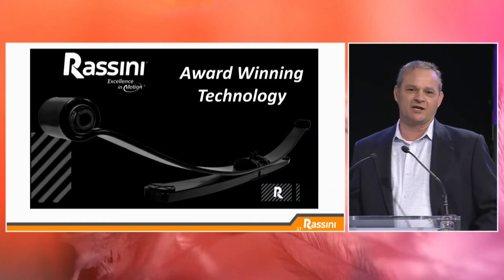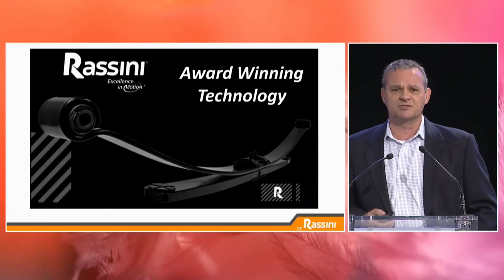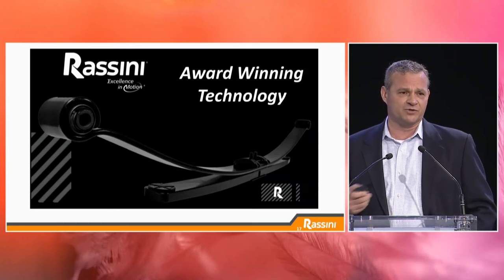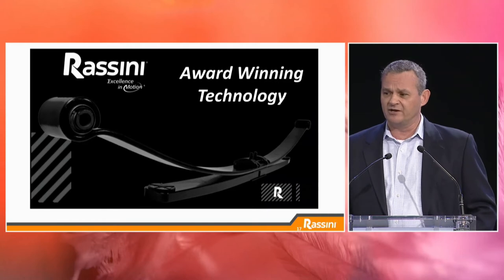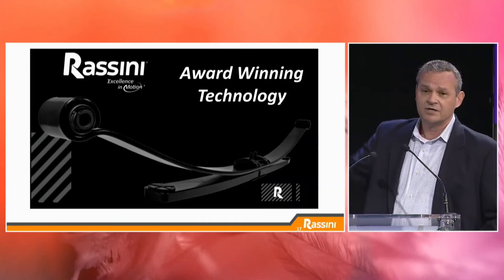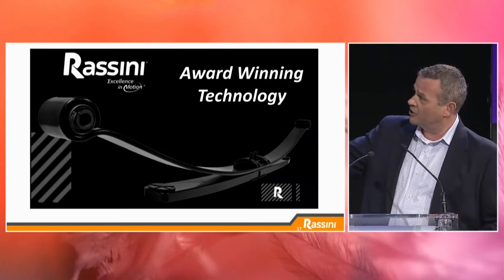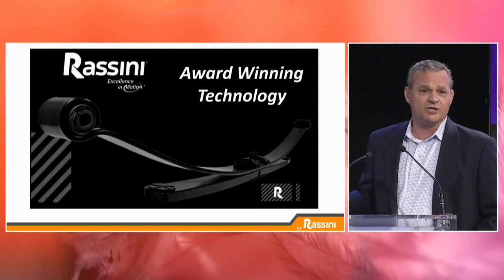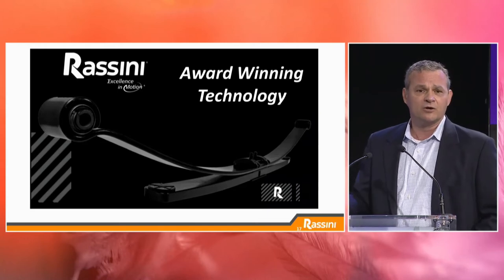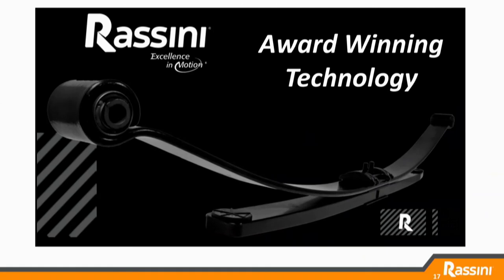Now, with this new exciting product, we've made a multi-material approach to our leaf springs. We've basically taken what would traditionally be an all-steel leaf spring, and we've lightweighted it, not just with the steel side of it, but also with a substitution material, a glass fiber reinforced plastic part. The top leaf that's arched is a high strength parabolically produced steel spring. And then underneath it, we call it a helper spring, which engages as the vehicle is loaded or goes through large articulations in the suspension.